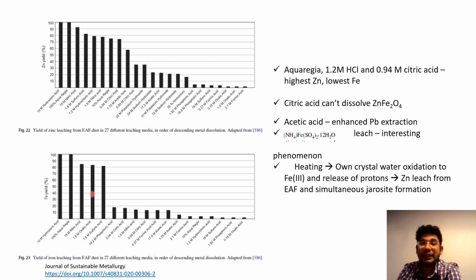Okay, anyways, the other thing I wanted to talk about is that somebody also tried this crazy looking ammoniacal iron sulfate and used it to leach. And they had an interesting result actually. This thing is pretty much alkaline, or at least neutral in pH, let's say, not really alkaline but not acidic at all. I think 8 to 9 pH. So they found that you have to heat it up. I think they heated it to 80, 90 degrees Celsius.